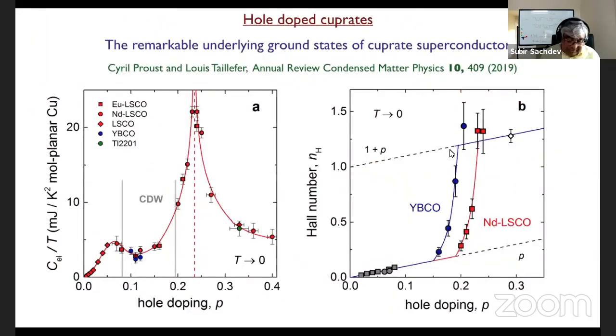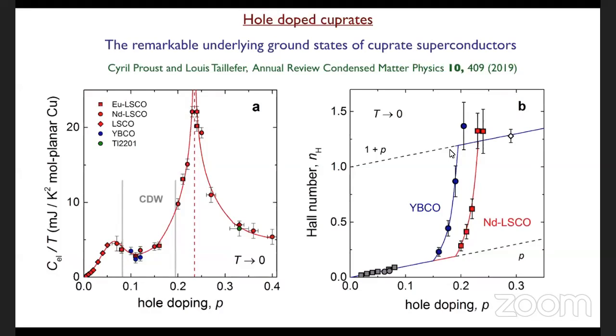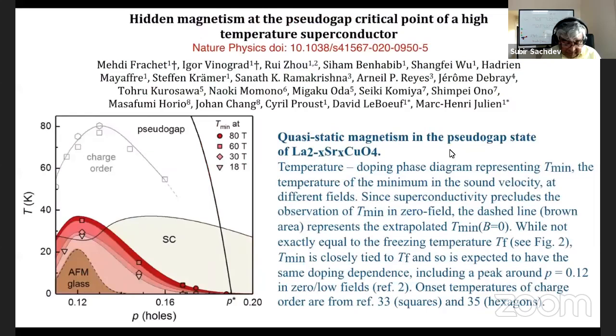Another important characteristic, which will relate somewhat to the model I present today, is that there appears to be a large peak in the specific heat, the temperature derivative of the specific heat, C over T, near the critical doping, and also in transport measurement, a jump in the carrier density. And finally, and this will be most relevant to the disordered systems I'll talk about today, there's also indication, at least in an applied magnetic field, of glassy behavior in the pseudogap regime at low temperatures, some kind of antiferromagnetic or spin glass.